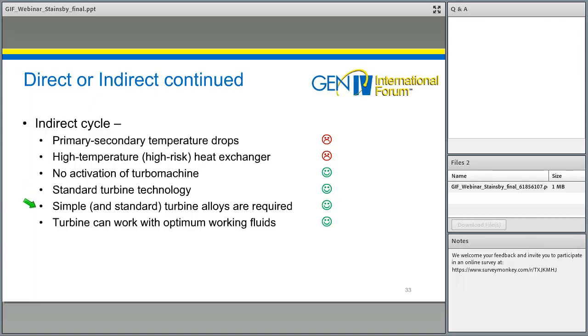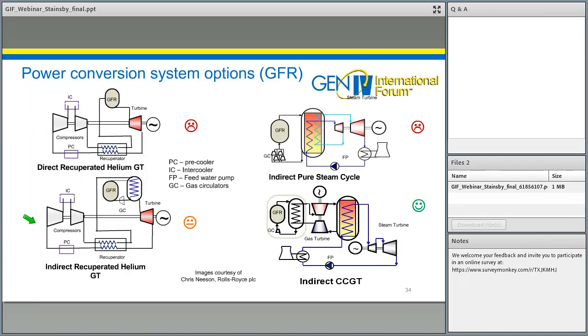liquid oil bearings. We can use standard turbine alloys, and we can have a turbine working with an optimum fluid, such as nitrogen. Most of the gas turbines in the world are designed to work with air, which is mainly nitrogen. So we are in the realms of well understood performance characteristics for turbines which could work with nitrogen, but we can't use nitrogen as a reactor coolant. So that's an advantage that the indirect cycle actually gives us.